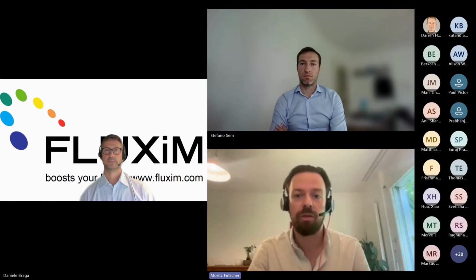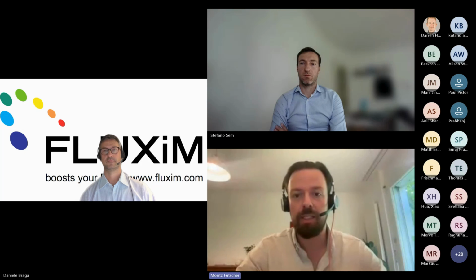Another one is the form factor. For example, the thinness of our cell. The thinnest batteries which you find today are in the order of 0.5 millimeter thick. We can produce them much thinner than that. And that's why we can fit the batteries into applications where previously it was not easy to integrate them. You can think of something like an RFID label. These are labels which are placed almost everywhere in all kinds of products to track the product. But there you cannot fit a battery inside easily. Here we offer a solution to integrate batteries into these applications, which then allows them to actively transmit signals.